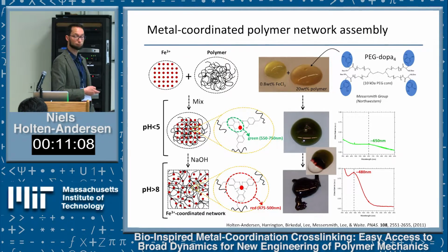All we do is just change the pH—we can easily do that by adding a little bit of sodium hydroxide. That should activate bond formation and also change the color of the complex, since it should absorb at a different wavelength. Here's a picture of a droplet of sodium hydroxide flowing into this polymer-ion mixture, and immediately where those two fluid boundaries meet, you get instant gelation. It's a very, very fast kinetic process.